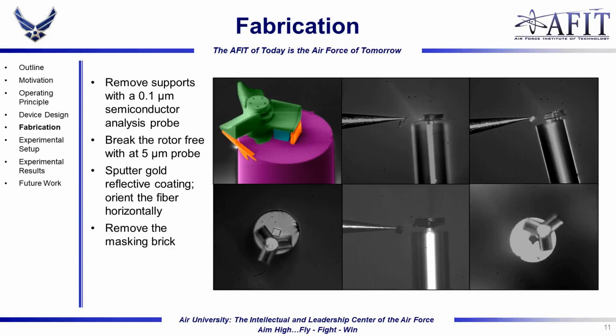The support structures are removed with a semiconductor analysis probe underneath a microscope and discarded. The device is then freed with a slightly larger probe such that the rotor rotates freely. Then the device is transferred into a magnetron sputtering system for the gold reflective film deposition.